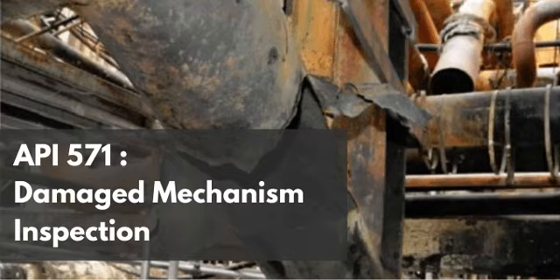And then there's the other documented case, an 18-inch diameter API 5L grade B pipe section. This specific section featured two 1-inch water wash injection nozzles running from the inlet to the second stage compressor. Right, the water wash nozzles. Yeah. Look at the common denominators here. Overhead knockout drums, reflux lines, and water wash injection nozzles. The uniting factor is the deliberate or unavoidable presence of free water. A water wash injection point is practically a manufactured ACSCC test cell.